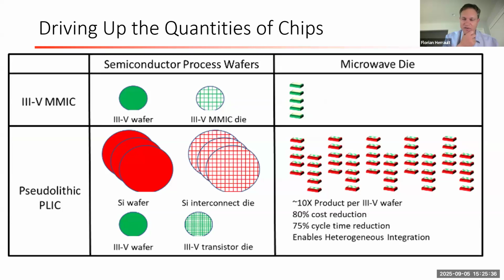So how does this drive up quantities too, right? A very interesting concept here when we talk about accessing leading edge gallium nitride and indium phosphide technology in these high mix, low volume foundries. Why would this be commercially relevant? Well, in a traditional MMIC approach, one such foundry may produce X wafers per month, and that will turn into tens or hundreds of MMICs per wafer. With our approach, which is a lot more manufacturing efficient, we now have 100x the number of transistors per source wafer. So with the same input of the III-V foundry, we can yield a lot more products.